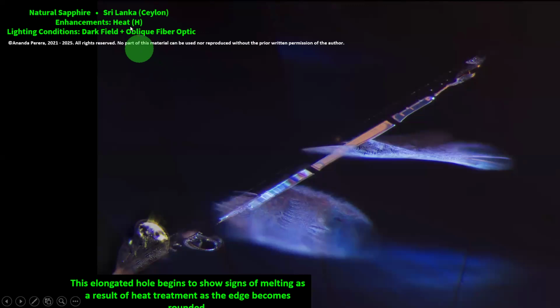What next here? Lighting condition here is dark field plus oblique fiber optic. There are two. Sri Lankan sapphire. You can identify it with very clear vision here. An elongated hole begins to show signs of melting as a result of heat treatment, as the edge becomes rounded, all the edges become rounded. So this is clear evidence of heat treatment. So it is a heated stone.